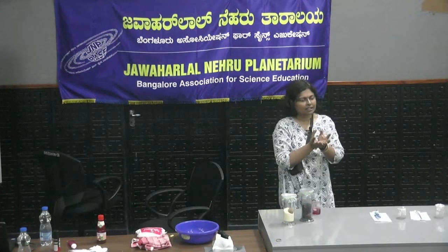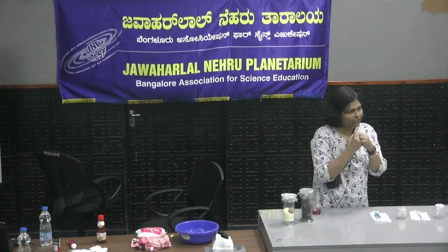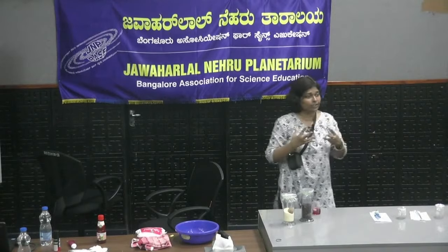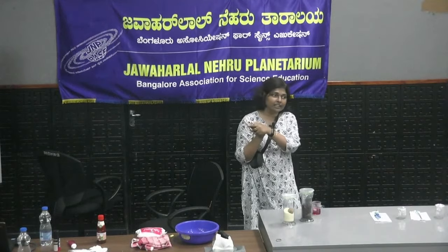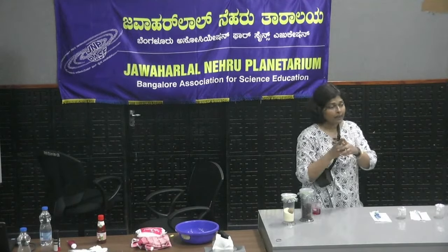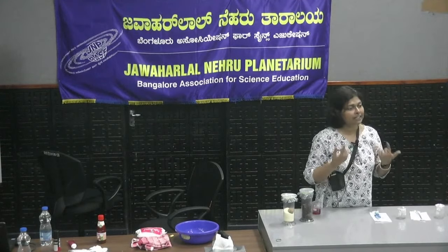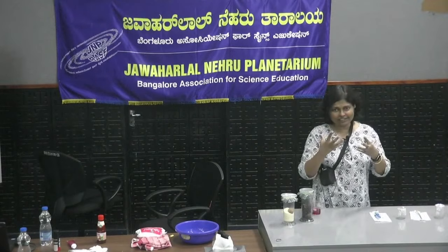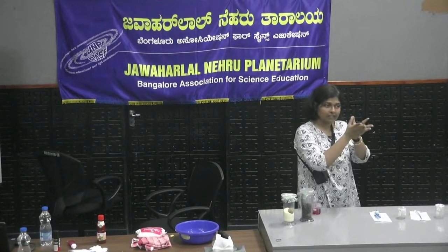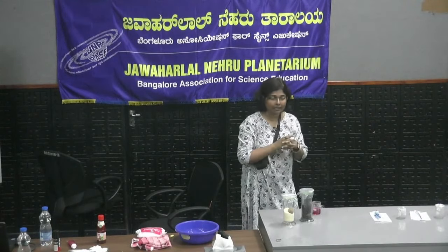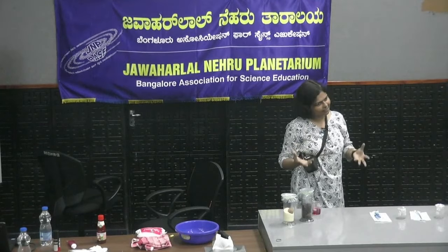What happens there is the material goes from hydrophobic to hydrophilic. Before it was hydrophobic, which meant that the material hated water, so it wouldn't let water in. It was coiled together, very much like in that dice-well experiment that I told you about. But as the temperature reduces, the material starts liking water for certain chemical reasons, and as a result it starts absorbing water and it can swell up. For certain polymers that we make, it swells exactly at 32 degrees, so it can sense the temperature.